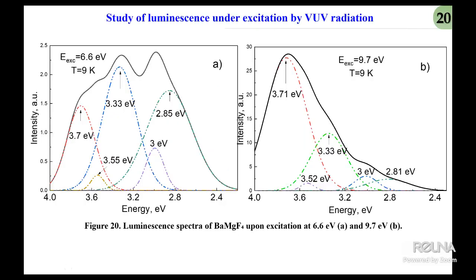The next slide presents the luminescence spectra of our ceramic materials recorded under excitation energies of 6 and 9 electron volts. Under 6.6 electron volt excitation, the luminescence spectrum exhibits a complex structure and can be represented as a sum of several components. The spectrum shows bands with emission energies of approximately 3.7, 3.3, 3.55, 3, and 2.85 electron volts.